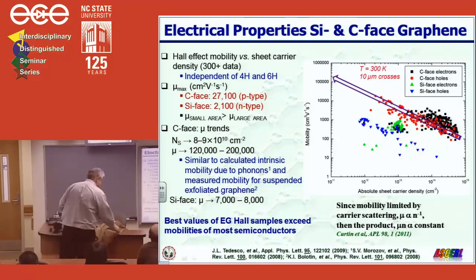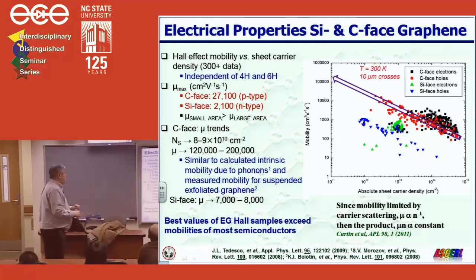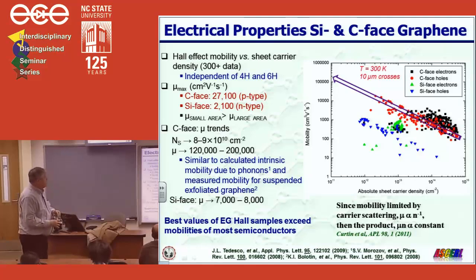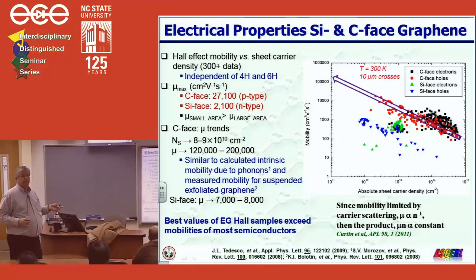So in this graphic on the right, you can see a summary of a large number of these Hall crosses that we measured for the samples. The red and the black boxes represent the carbon face material, and the blue and the green boxes represent the silicon face material. Notice the silicon face material is always below the carbon face. That's really the message to take home. There's something limiting the transport properties between the two.